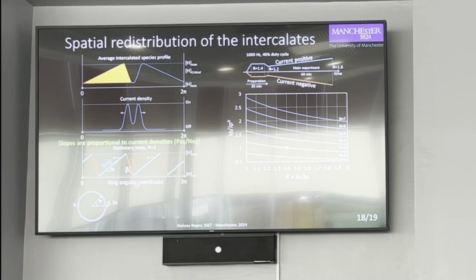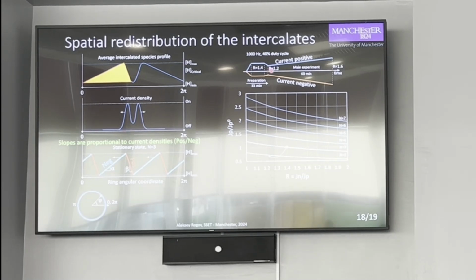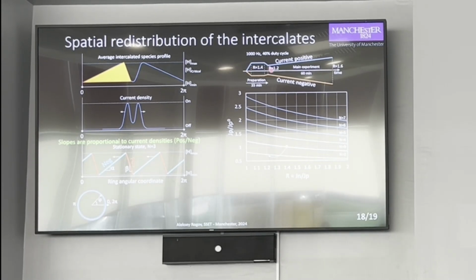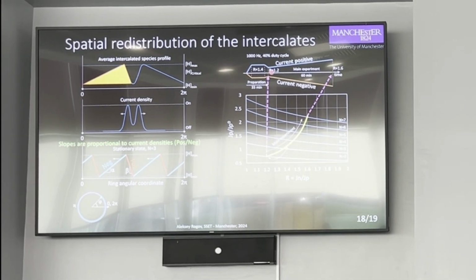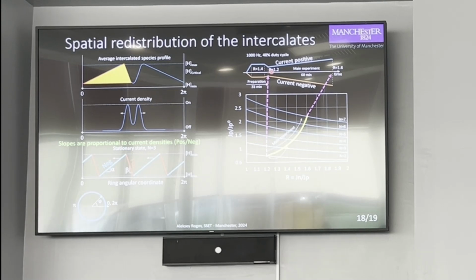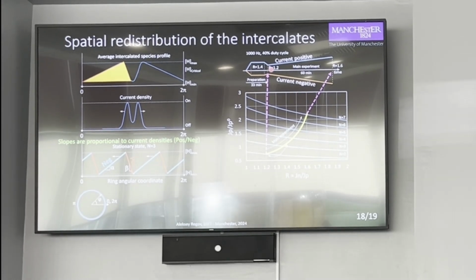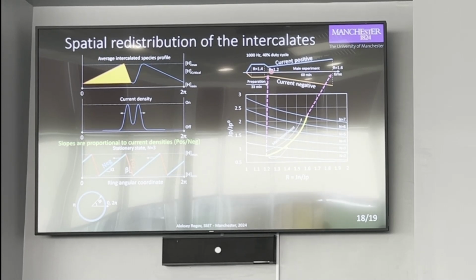To achieve this in experiment, firstly, we carried out an experiment for about 33 minutes in a regular steady PEO process until soft sparking was achieved. After that, we switched the process into the starting point and then provided a ramp for positive and negative currents in such a way as to pass the process through this yellow line, which crosses all of these pre-calculated values of characteristic combinations.